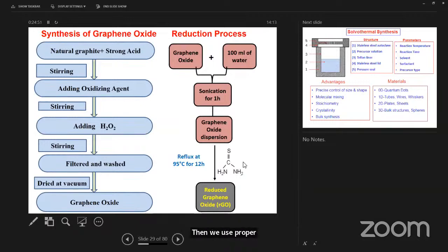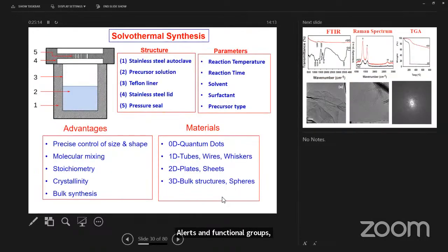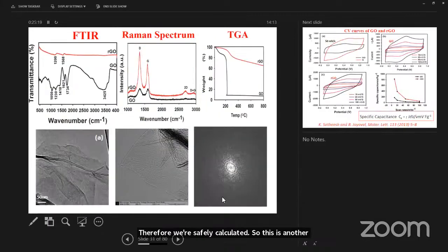Here we have used thiourea as the reducing agent. Refluxing it at 95 degrees Celsius for 12 hours, you get the reduced graphene oxide. If you are able to reduce all the oxygen functional groups in the matrix, then we can call it graphene. But in the chemical reduction process, there are always some residual oxygen functional groups present in the matrix. Therefore, we safely call it reduced graphene oxide. This is another technique, called the solvothermal technique, which is also useful for graphene synthesis, and many people have used that one. So once you prepare the graphene, there are three major fundamental studies used